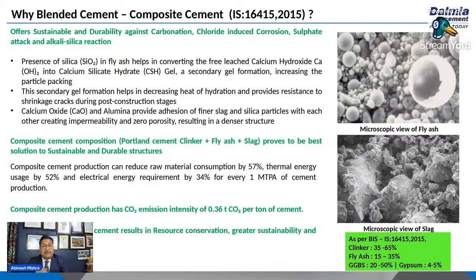If we go through the microstructure, composite cement is actually made with slag, ground granulated blast furnace slag, and fly ash. The top picture on the right-hand side denotes the microscopic view of fly ash, which is spherical in nature, water absorbing, and amorphous. The second one is slag, which is angular, glassy, and has many corners and crevices. All these things make a perfect combination for preparing a cement made with slag, fly ash, and clinker, obviously.